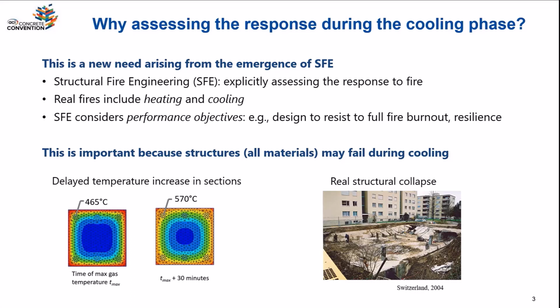At the same time, we recognize that failure during cooling can happen. That's true for any type of building materials, primarily because of delayed heat transfer. There are other effects, strain reversals, further degradation of strength, etc. But primarily, once the heating stops, the inside of the sections, the core of the structure will still continue heating for a while, and so the load-bearing capacity continues to decrease. And we've observed in real fire some structural collapse during the cooling phase.